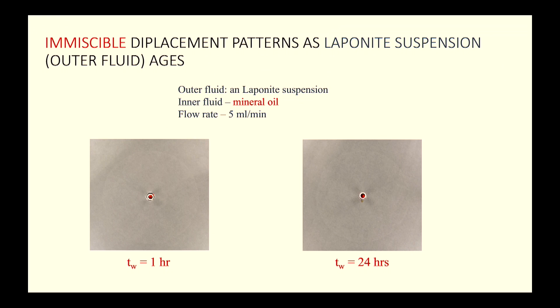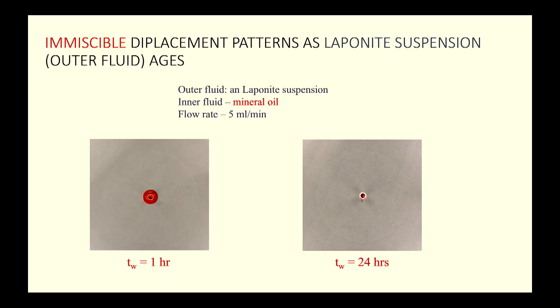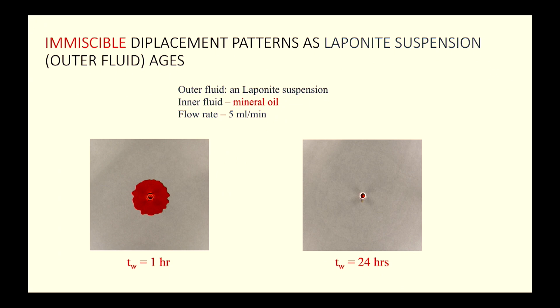When oil is injected instead of water (immiscible case with surface tension), the behavior changes. At one hour of aging, there is an initially stable interface that grows, then tiny protrusions develop. After that initial stable growth, fat protrusions develop — called the flower pattern. Surface tension stabilizes the interface, making propagation much slower.